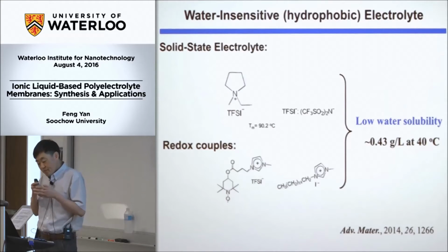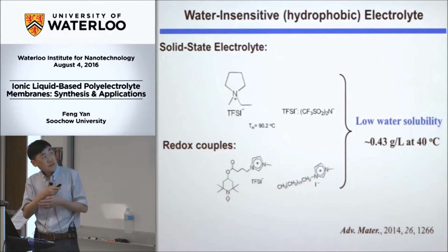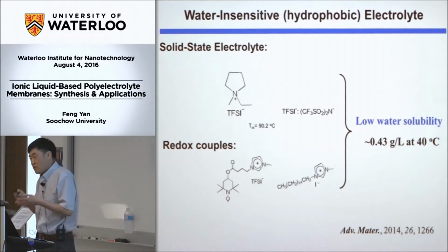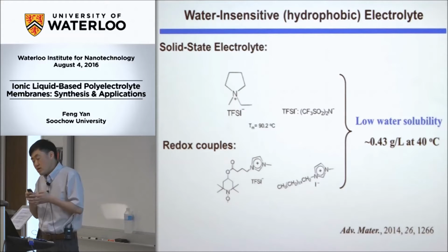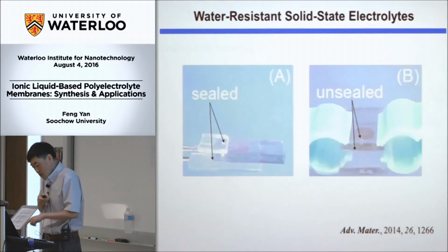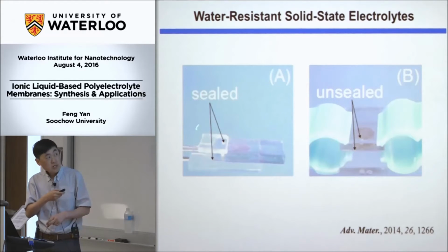So what we did was synthesize a solid-state electrolyte where the compound itself is hydrophobic. It should not be sensitive in the air, and the redox couples are also hydrophobic, and you can see the very low solubility in water. And we fabricated two devices. One is very well sealed, sealed with glue and tape.